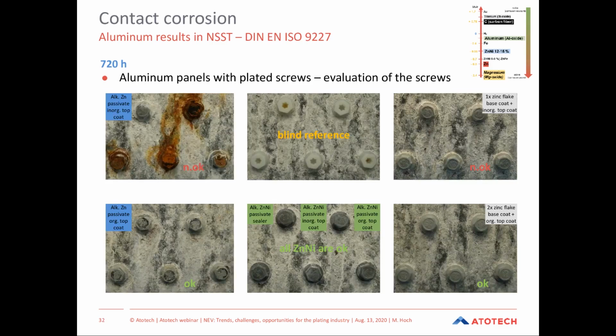In this slide, we see the results already after 720 hours in the salt spray test. The blind reference is shown in the middle of the page. Zinc plating with organic top coat can survive these conditions, whereas zinc plus inorganic top coat shows severe red corrosion. So this is on the left side of the slide. The same for zinc flakes: organic top coats show positive results. Inorganic top coats fail, which is probably hard to see on this picture. I put a non-OK here. You see some red corrosion at the borders of the screws. Zinc nickel shows by far the best results with all plating sequences.